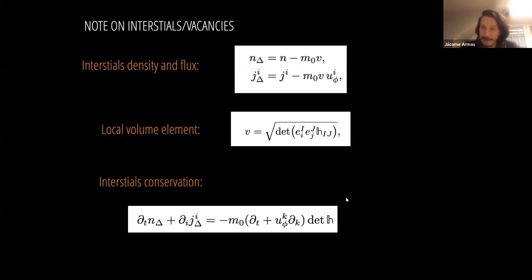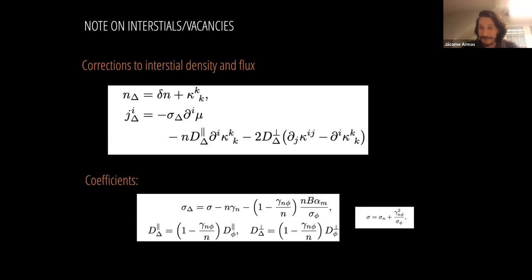of the reference metric. So what this tells you basically is that if you want interstitials to be conserved, you have to require that there cannot be any changes in volume due to plasticity. So you have to require this material derivative to vanish when acting on the local volume element. As some of you might know, I know that Jan knows very well, when you demand this to be zero, this is basically the glide constraint.